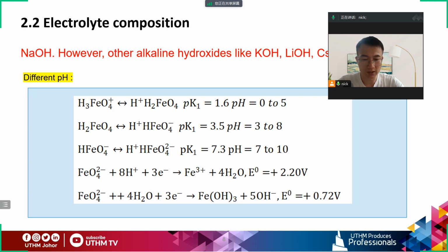The second factor is electrolyte composition. The electrochemical synthesis of ferrate is typically carried out under strong alkaline conditions, with the main electrolytic solution being sodium hydroxide, and other alkaline hydroxides can be used. The electrolyte carried is pH. Under acid and neutral electrolyte conditions, ferrate rapidly oxidizes with water to produce ferric and oxygen, which can be directly employed for pollutant degradation.